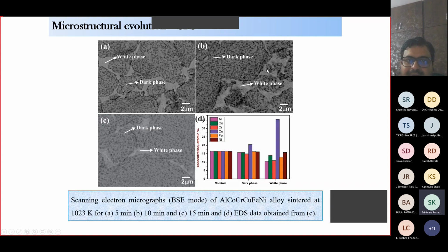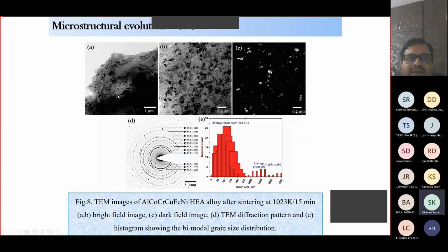And that two-phase morphology can be seen in the SEM micrographs. And this is the chemical analysis that was done using energy dispersive spectroscopy. So this is the nominal composition of all the elements, and you have a dark phase, black one here, and a white phase. And the white phase is higher in copper content. And these are the transmission electron microscopic images of this two-phase system. And you have a two-phase presence that we could see from the electron diffraction pattern. And the grain size is also increased, say from 10 nanometers in the milled condition to 112 nanometers.